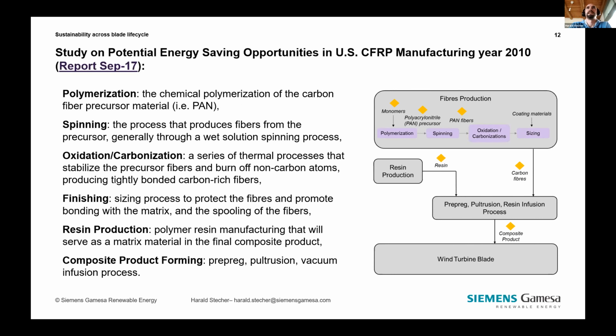Main flow diagram is the same, but the steps for the carbon fiber manufacture are shown. So precursor monomers are polymerized to form precursor fibers, which then undergo an oxidation and carbonization process. And at last, the sizing is applied and the fibers are further processed to roving and mats. To save on CO2 emissions, the same actions as before can be taken for the resins, so carbon fiber.